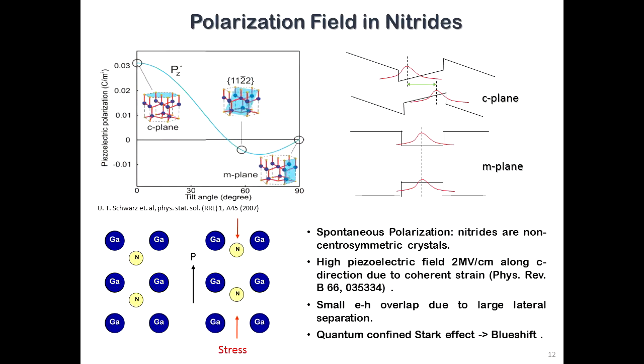But it comes with other problems also. They are in the hexagonal structure. What you have are two hexagonal close packs telescoped into each other, the gallium plane and the nitrogen plane. And they are polar crystals, so you have a spontaneous polarization. In addition, they are non-centrosymmetric, so there is a strain-driven electric field, which is the piezoelectric field. As a result, the band alignment is very funny, and for an optical device, the electron and hole wave functions don't overlap, and this causes some problems.